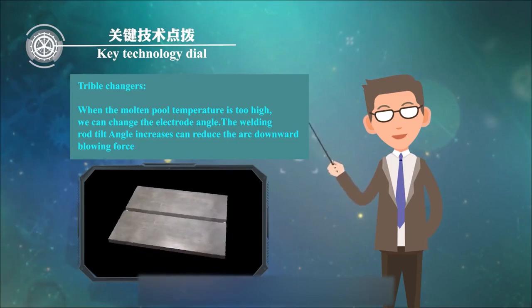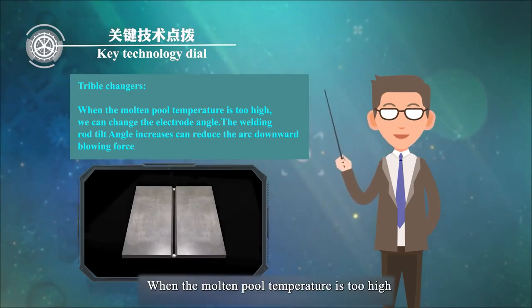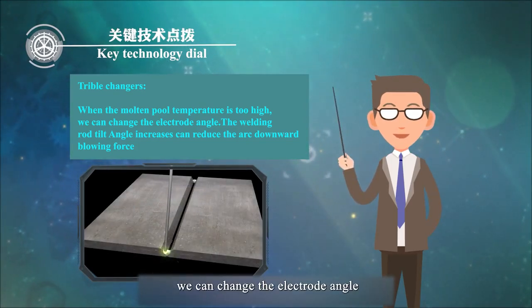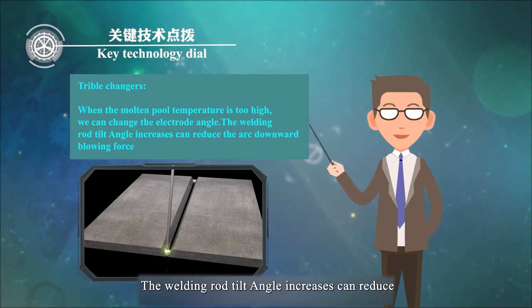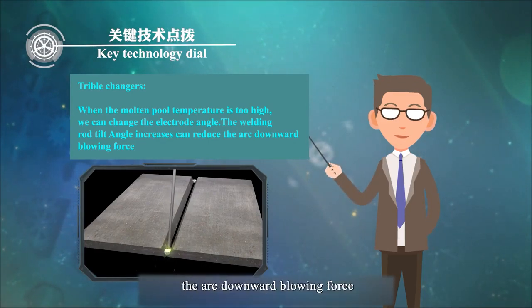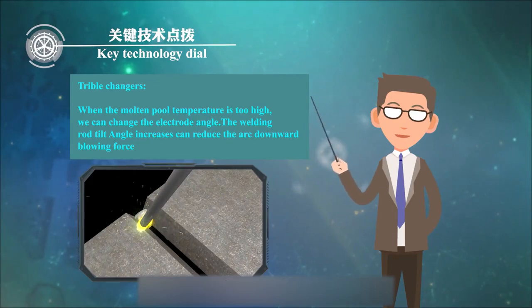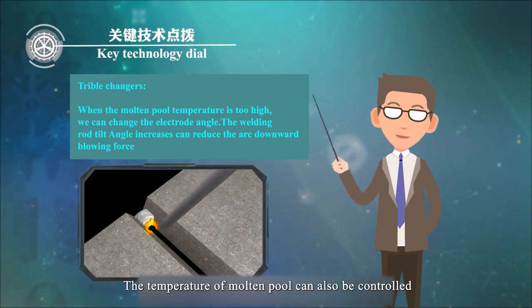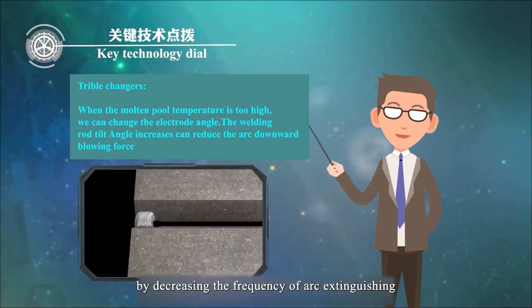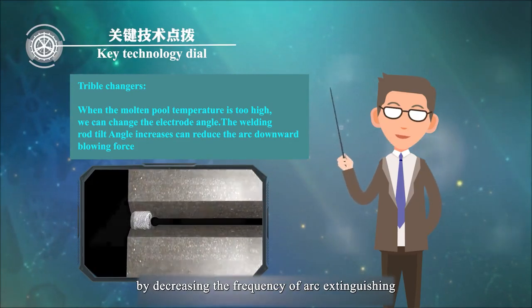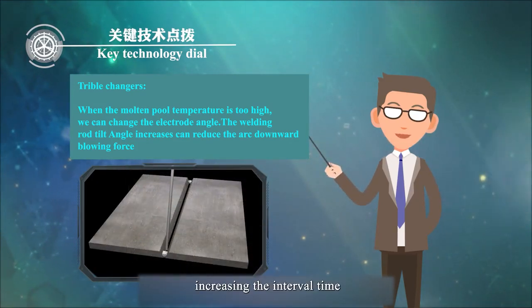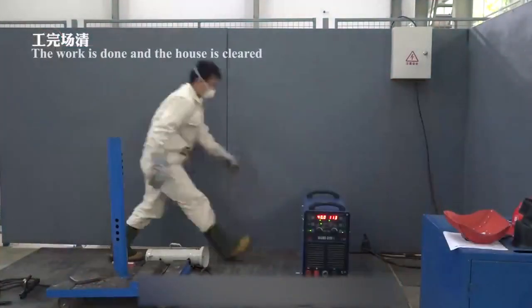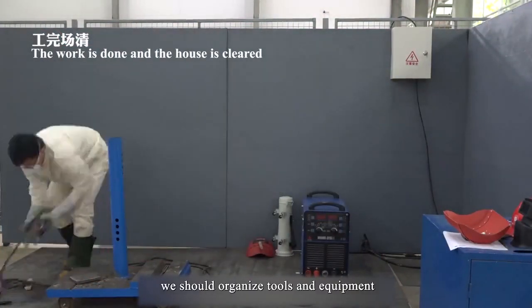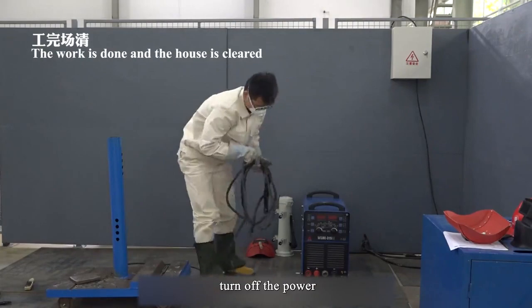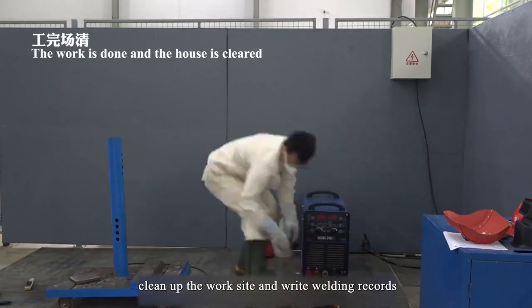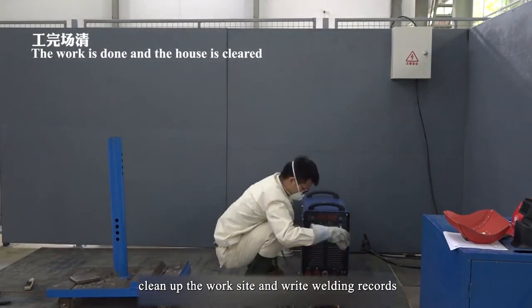Thirdly, adjust. When the molten pool temperature is too high, we can change the electrode angle. Increasing the welding rod tilt angle can reduce the arc downward blowing force. The temperature of molten pool can also be controlled by decreasing the frequency of arc extinguishing, that is, increasing the interval time. After practice, we should organize tools and equipment, turn off the power, clean up the work site, and write welding records.